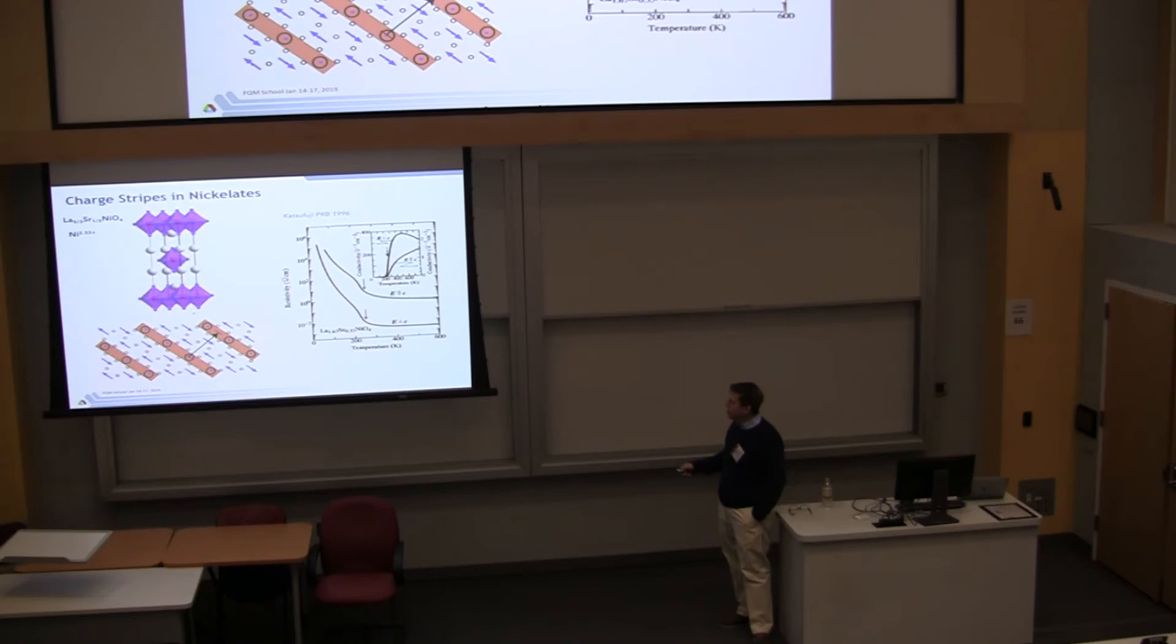And the stripe phases, so this is the material that everybody studied. It's a single layer, so-called single layer nickelate. It's a layered perovskite. And here you're seeing the resistivity as a function of temperature. And they form these semiconductor or insulator transitions. And using neutron diffraction, John Tranquada and others, S.-W. Cheong showed that that's due to a real space ordering of charge and spins into these stripes. Okay? And so this is a competing ground state with superconductivity.